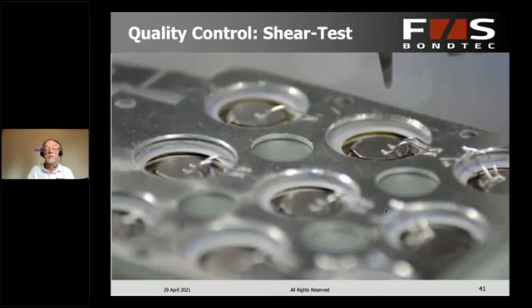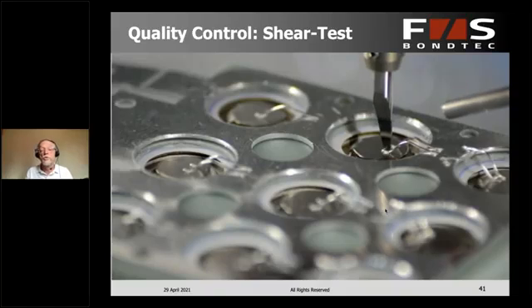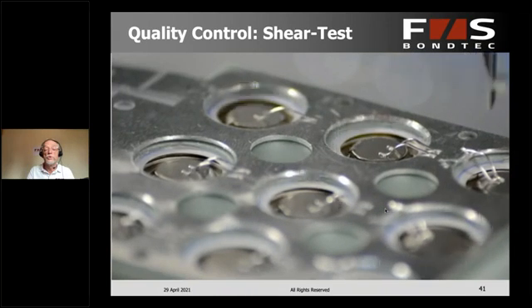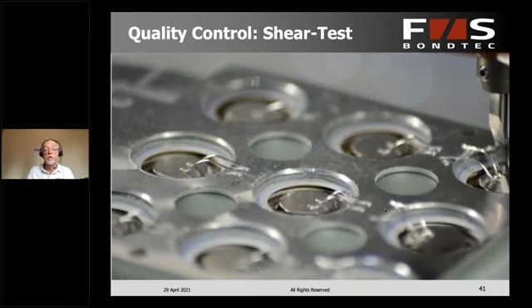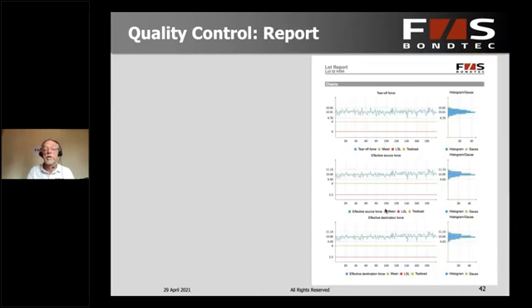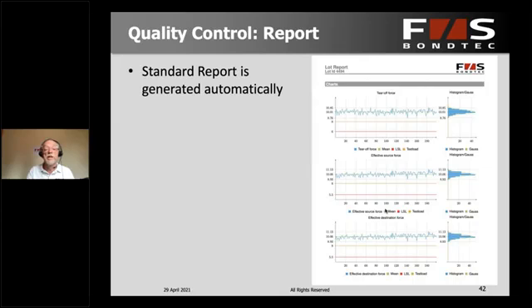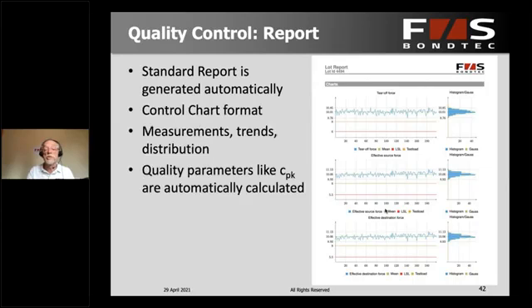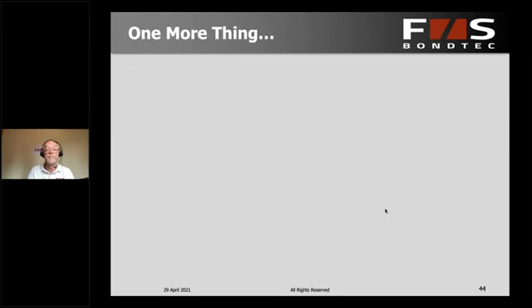The second test is called a shear test. There you do not pull on the wire, you just push at the connection itself, and again measure the force at which it fails to give you a quality control measure. And of course, like in any quality control, you get a report out of this, which comes out automatically. You get a control chart, you get measurements, trends, distributions, CPK values, and so on, and also customized reports.